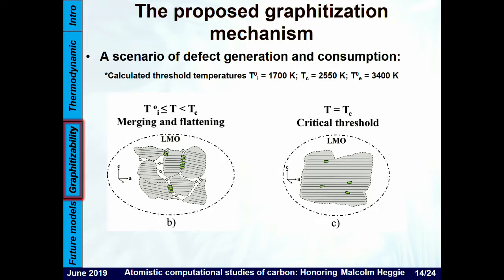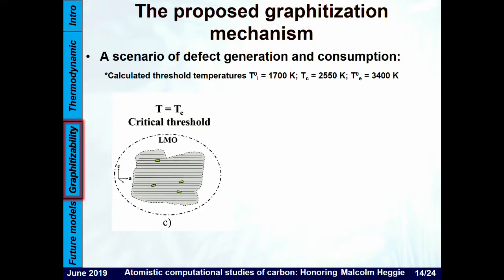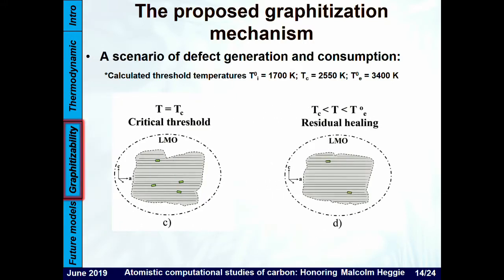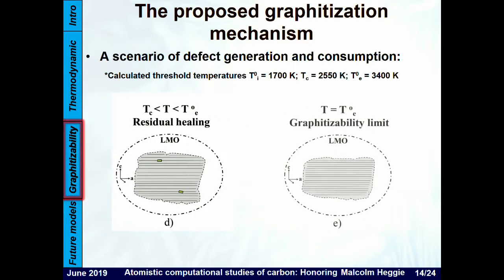As you continue to increase the temperature and reach the critical temperature of 2550 Kelvin, both the intercrystalline matter and the cold crystalline phase have completely merged, and all you have is a single body inside the LMO, but this body might or might not have annealable topological defects in its structure. As you heat treat it at higher temperature, these defects will progressively anneal, and at around 3400 Kelvin, all defects are removed, the material has finished graphitizing, and nothing will change even if you heat treat it at higher temperature. So this is the scenario of the model, this is how we represent it.